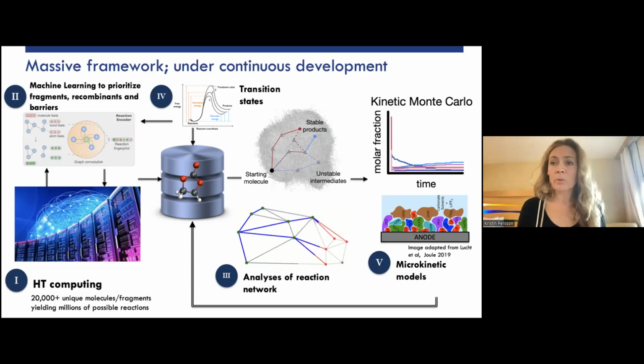It's not all thermodynamics. Once you have some paths you like, you have to refine them with kinetics, and we're working on machine learning kinetics, which is much harder than thermodynamics. Once you have enough of that data, you have to start tracking which are the steepest descents in the thermodynamic landscape, refining them with kinetics. We do that with stochastic algorithms and mathematically accurate algorithms such as Dijkstra's and Yen's algorithm. And once you have enough paths that you trust, you can start looking at the competition between those select paths with kinetic Monte Carlo. And I hope to show you some of the things we've done, and that we're getting to a point where we believe that parts of this actually do work.